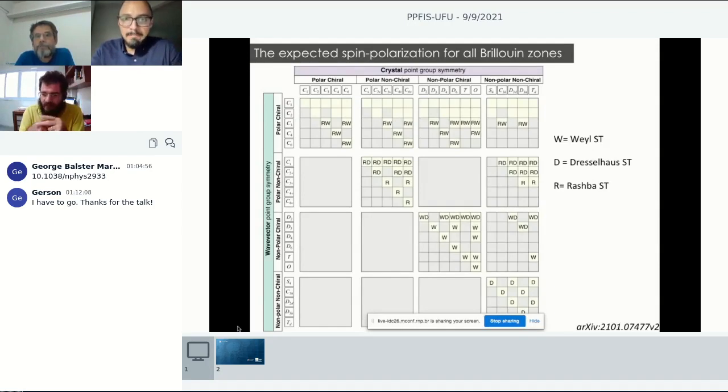Good. Second thing, when we talk about measuring spin polarization, it should be momentum selective, because if there is no time reversal symmetry broken, the total spin current should be non-polarized. But if you are able to focus to collect a spin from a particular point or region of the Brillouin zone, then you should have polarized, but not if you don't select the momentum, right?